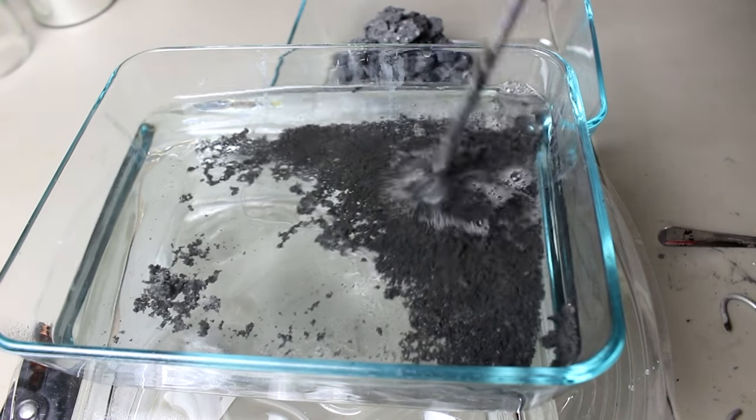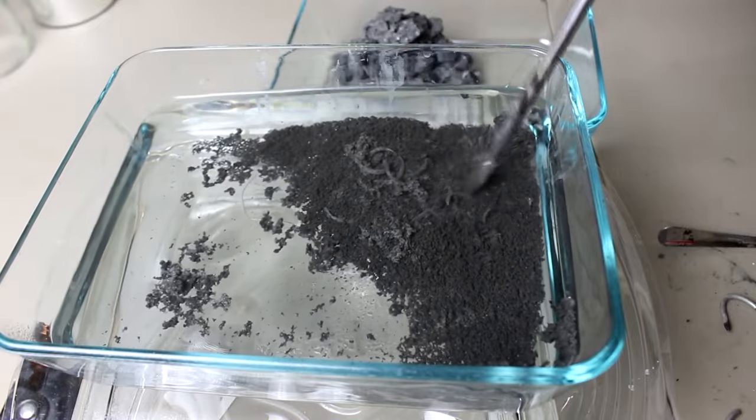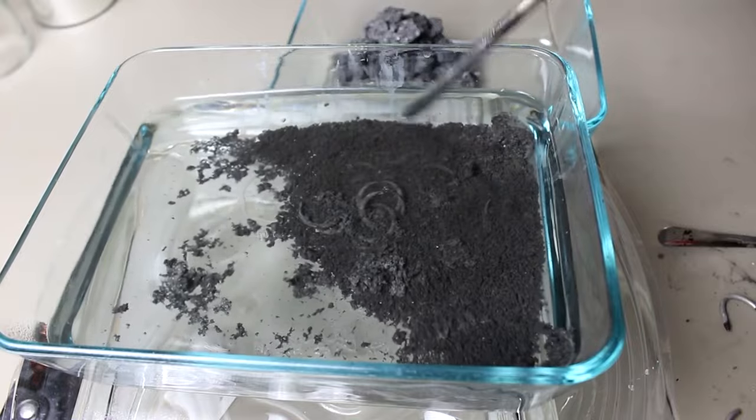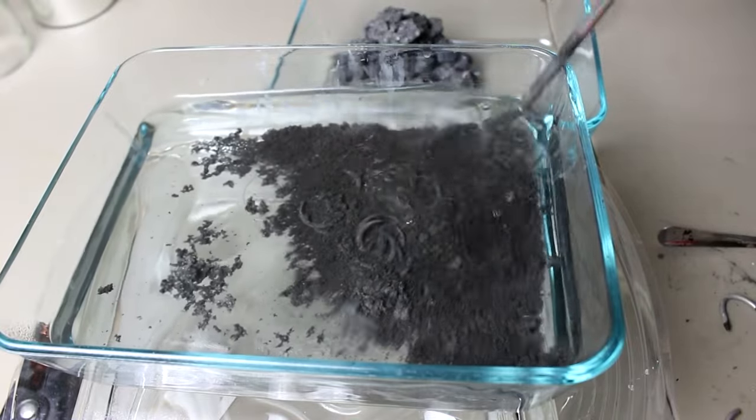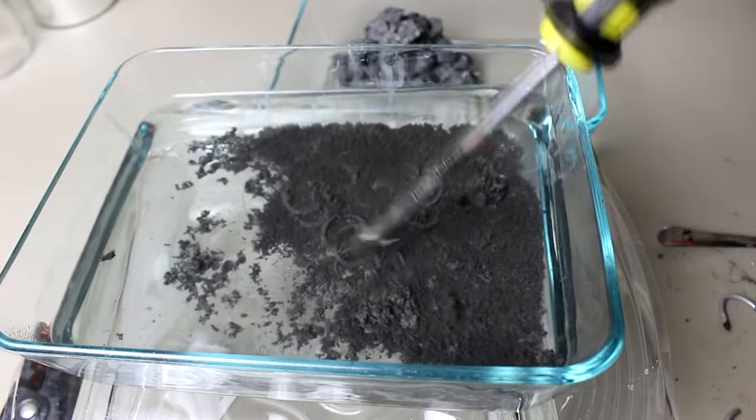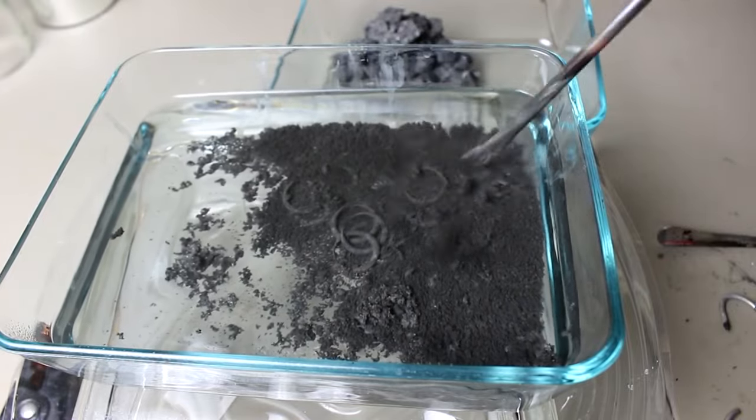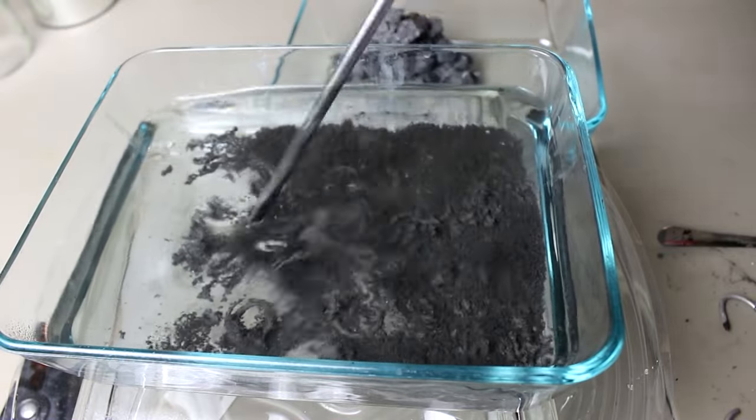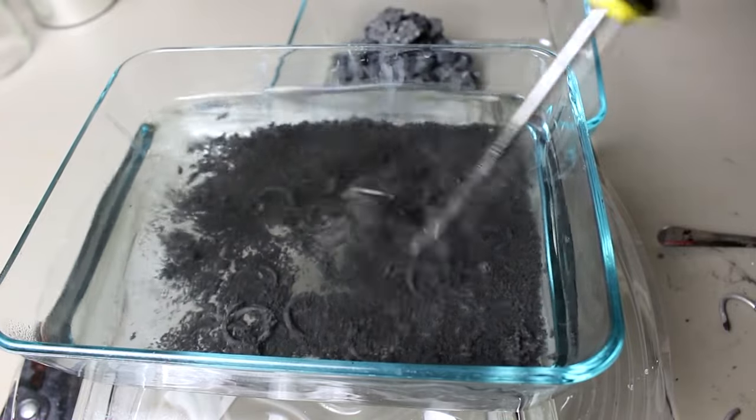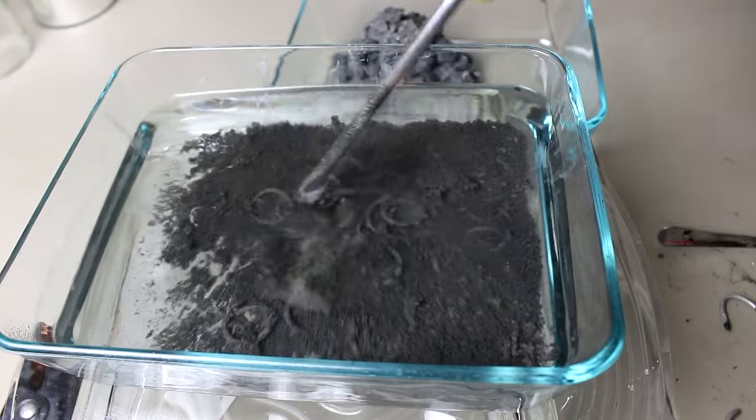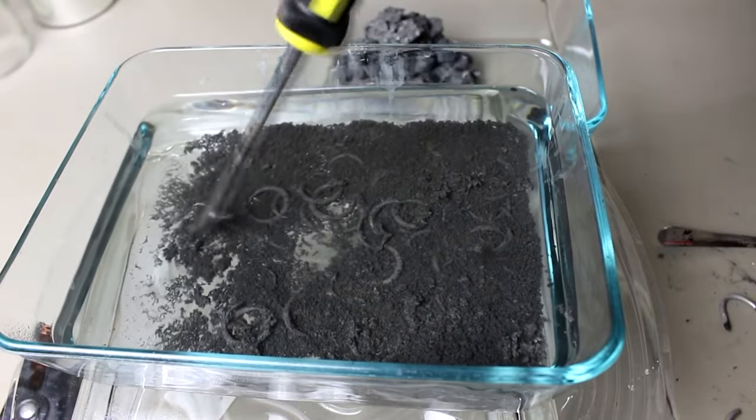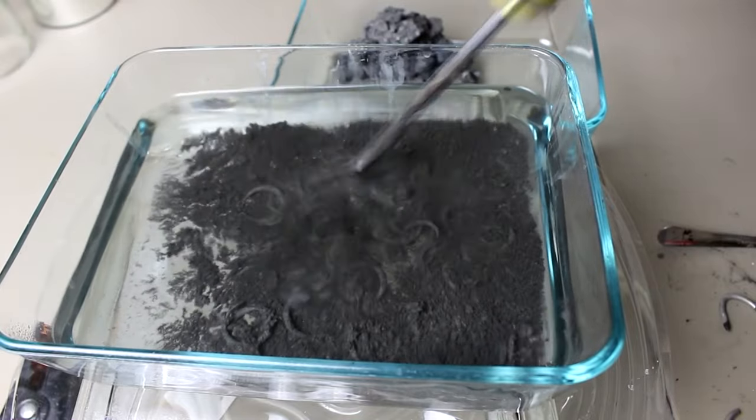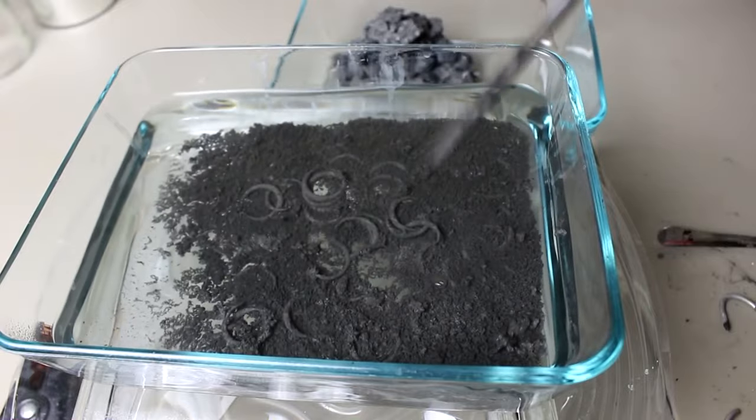And what we've got left in the dish, there's a couple of chunks of it in there still. You can kind of see. But primarily, it looks like I've just got like copper and silver powder. So, I'll tell you what I'm going to do. So, I'm going to pull out the bigger chunks of tin after I break off all the little bits of silver and copper from them. And I'm just going to let this sit in the acid overnight. I may even dump off some of this and strengthen the acid a bit to dissolve away these stray pieces of tin crystals. And then, once we've got that, then we can process it to extract the silver from the copper.